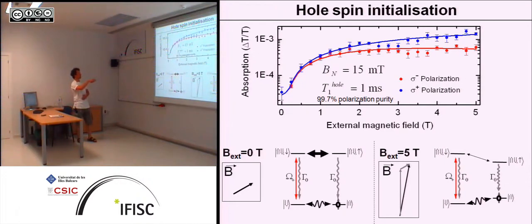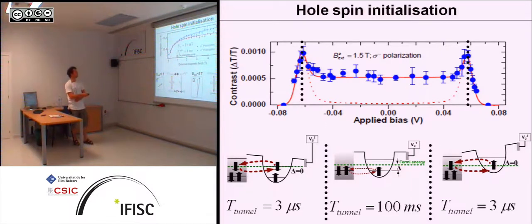And the solid line here is a fit with the 4-level density matrix equation. So that's not some averaging or something. That's really fitting the quantum dot consisting of tens of thousands of atoms with a model intended for one atom. So it really shows how equivalent they are, at least in this experiment. Okay, and the important thing is that we get a hole spin relaxation time. We extract that out of the theory of 1 millisecond, which for quantum information processing is very, very long. It's a good result.